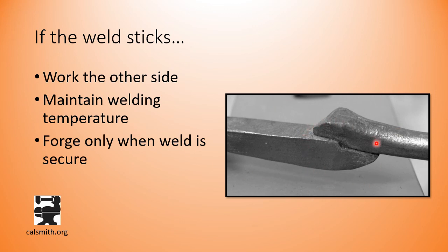The weld is going to continue to strengthen anytime you have it at that welding temperature, whether or not you're applying pressure. Again, if you hit this too cold, it will cause the weld to fail. Once your weld is secure and you're sure of it, then you can start forging this piece.